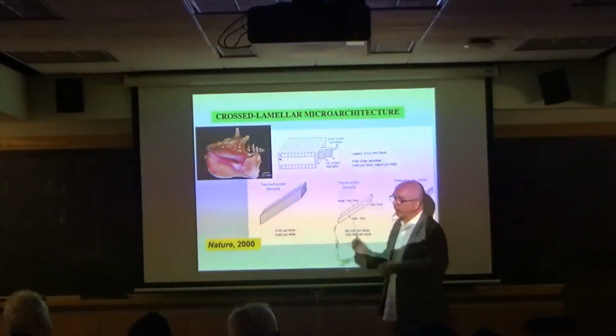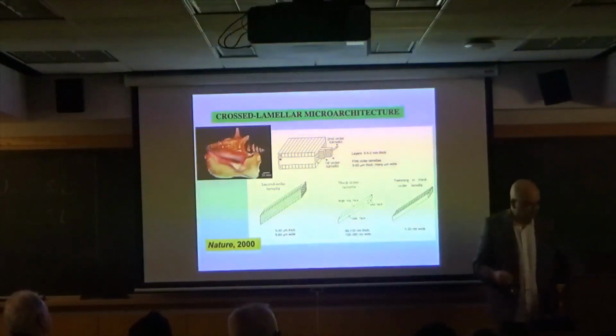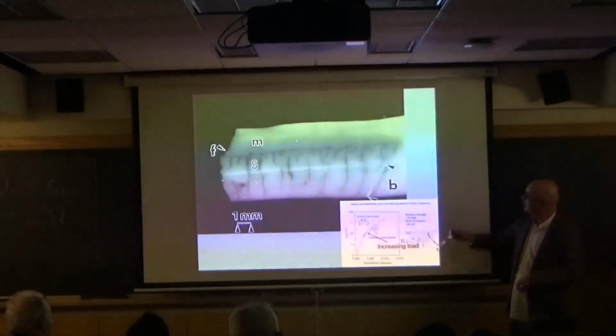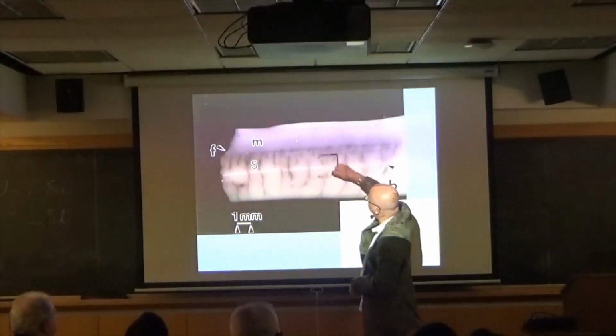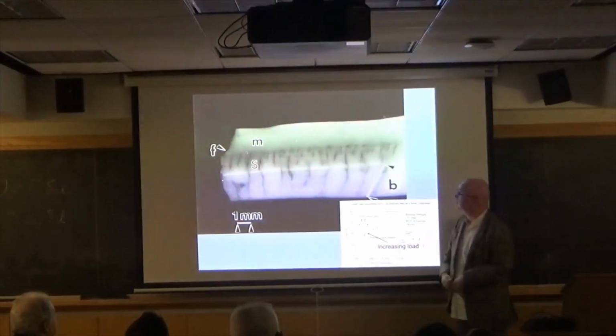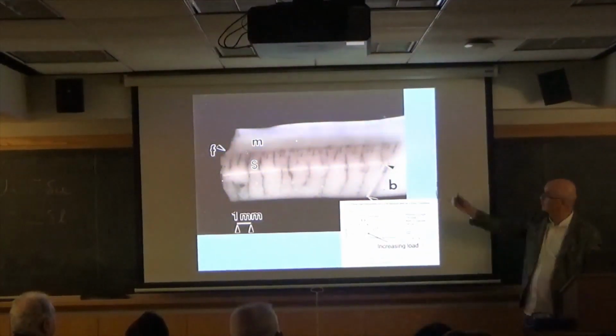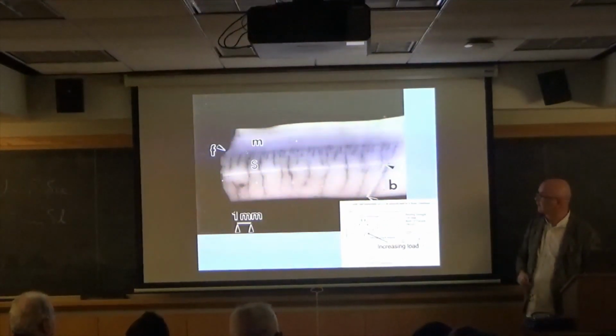Well, you could solve all this problem. Well, again, now you have the formalism, and you calculate it. Again, these are actually the experiments that we ran where you see all these cracks that develop and eventually saturate. The fracture toughness of this thing is about 3 orders of magnitude higher than the ceramic itself.